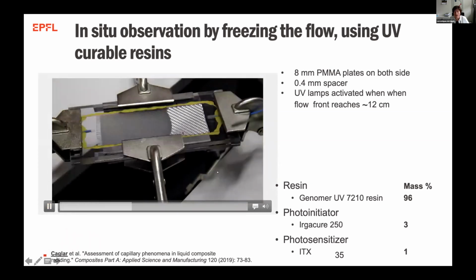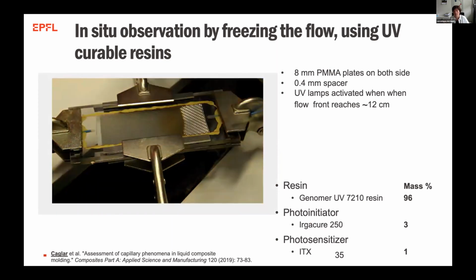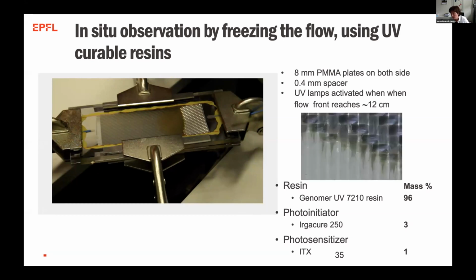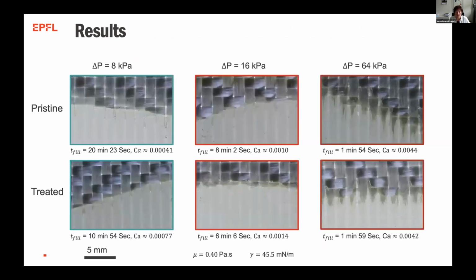the resin flow, and then at a given time, I illuminate with the UV, and the resin stops flowing because it's cured. Of course, it works only for very thin resins and so on, and we're working on improving this idea. But we can stop, and we can observe then a posteriori what the flow front looks like. And that's where you found those nice pictures that I showed you recently. So, if I do this, then I can look at the results, and I can compare again this pristine and this treated fabric that I use as a fil rouge for this presentation.